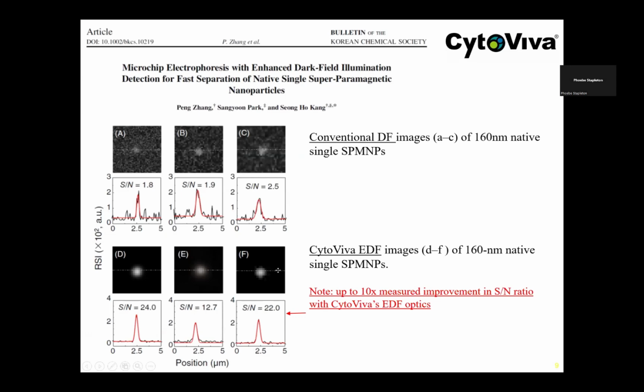And you can see a very clear difference just qualitatively in the signal to noise ratio. But when they measured that in a highly quantitative manner, they measured about a 10x increase in the signal to noise improvement. And what this means from a practical perspective as it relates to CytoViva is that you have the ability to observe engineered nanoscale materials, metal oxides, polymers such as these plastics and such, well below 50 nanometers, metal oxides and noble metal materials down to 10, 20 nanometers.